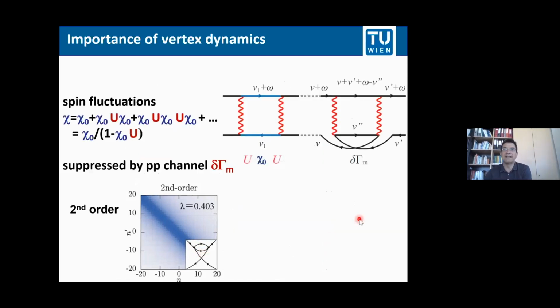And what this particle-particle contribution is doing, if you calculate the antiferromagnetic spin fluctuation, as you know, you have this RPA ladder, you have a U, a chi0, a U, and this kind of diagram with two particles here just has a particle line instead of a hole line, and therefore it has the opposite sign, and that suppresses your vertex. And as you see here, for the frequencies, nu plus nu prime have to be 0. And that is why you get this side diagonal where you have the strong suppression.